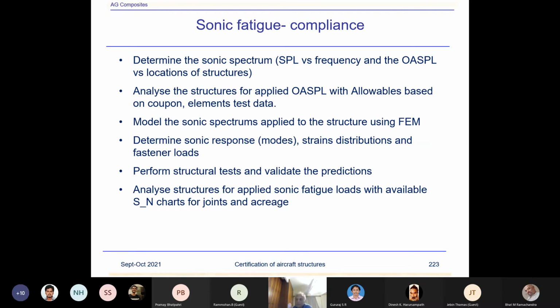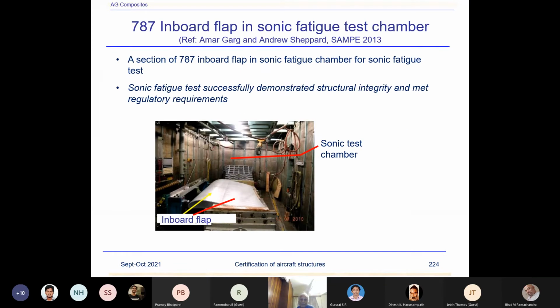So there are charts which are prepared for the fatigue life. It's a high cycle fatigue. It's not easy to determine the allowables also for high cycle fatigue. So that is how the compliance is done, and also testing the component. During the 787 program, we tested the whole component. I think I've shown over here. So during the 787 program, the compliance was done through analysis, supported by the test evidence.